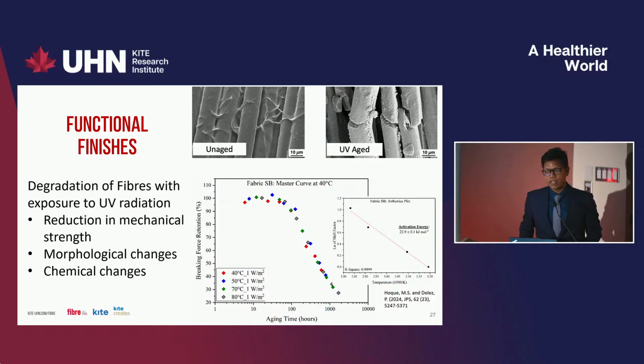We studied different fabrics in total. Here in this study, you can see the result of 3 fabrics, but we studied 8 in total. We exposed the fabrics to artificial light, fluorescent light, at different UV irradiances. And you notice that, for example here, after exposing the fabric for 240 hours, we saw cracks on the fiber. That was not visible on the surface, but at the micro scale, there were cracks in the fibers.